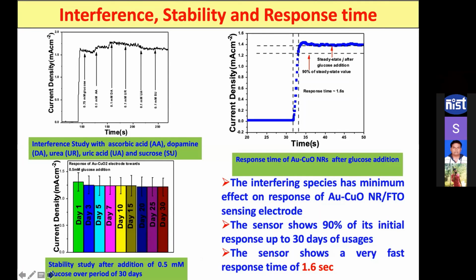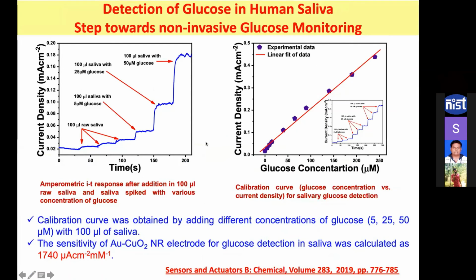And after 1 month's use, there is only a 10% decrease of sensor current. So this is highly sensitive, highly stable, and the response time is very fast, 1.6 seconds. So here is the detection of glucose in human saliva. We collected human saliva from different volunteers, but we could not collect saliva from diabetic people. So that's why we simulated saliva at different concentrations. We add glucose at different concentrations in saliva collected from healthy people. So that is simulated saliva.